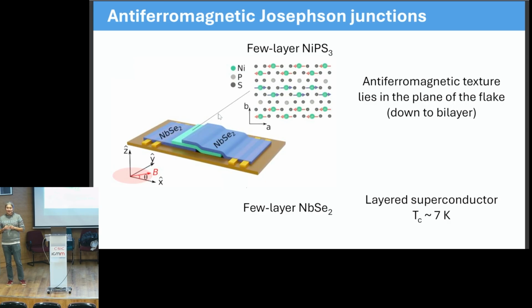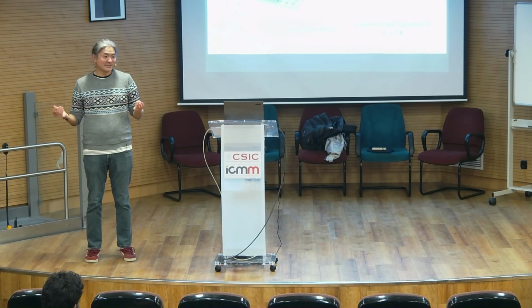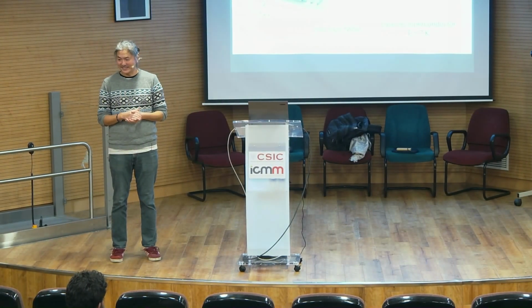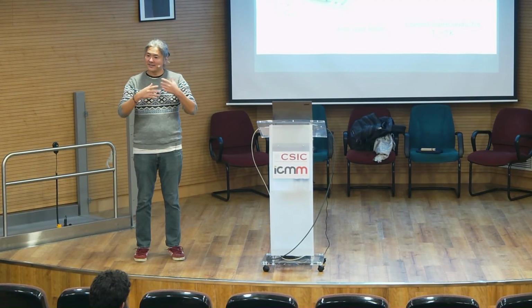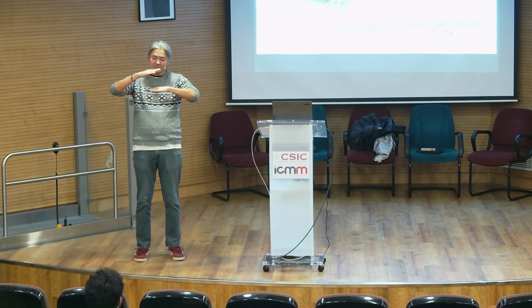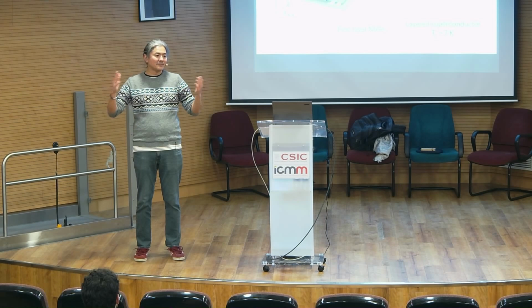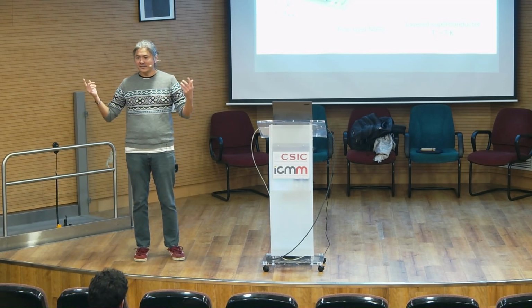Now, we have measured a few samples because, of course, you see this and you wonder, could it be by chance? The thing is, with this material combination, we see a response that is consistent with two localized channels, sometimes just one, but we don't see extended areas where it conducts. But as I mentioned before, it's very tricky to work with this sample. You prepare a batch and then you measure, and a few of them don't work at all, because these are three layers stacked on top of each other, and you have to have really good contact between each pair. Some just don't conduct. There is very high resistance.